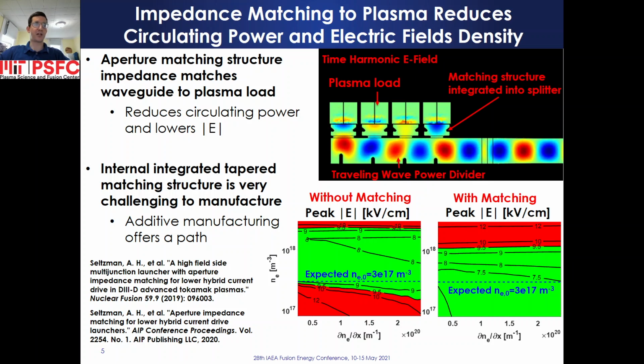An impedance matching structure, consisting of a thin inductive tuning element, is integrated into each waveguide aperture to match waveguide impedance to plasma surface impedance. Lower reflection and circulating power reduces electric field compared to launcher designs without a matching structure, improving reliability in coupling power. The complexity of the matching structure and traveling wave divider is enabled by additive manufacturing techniques.